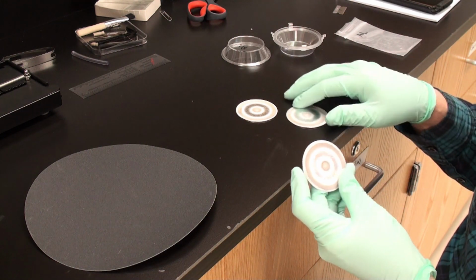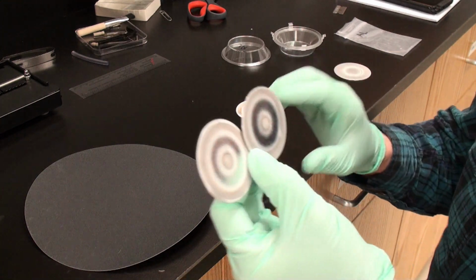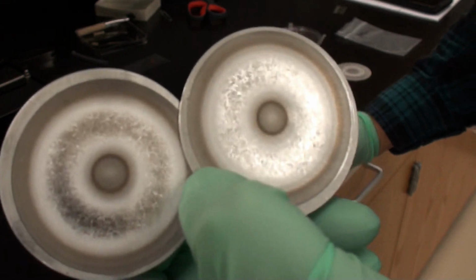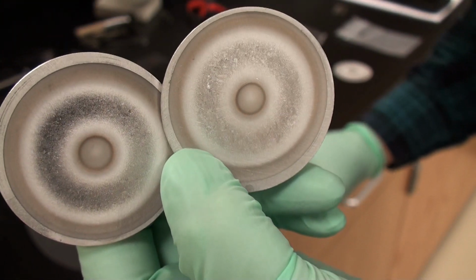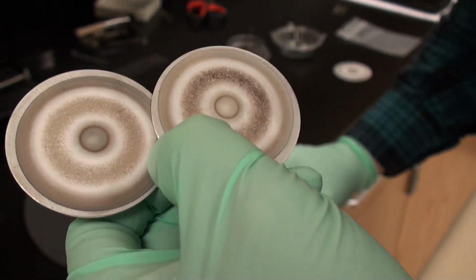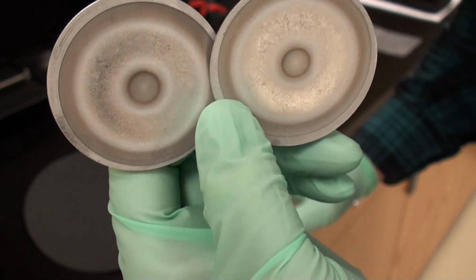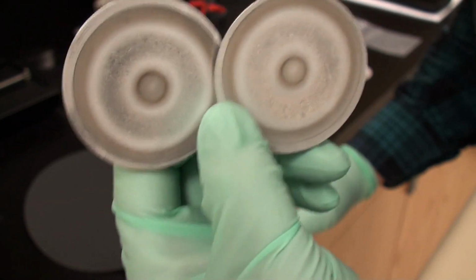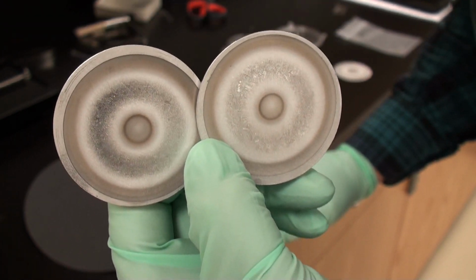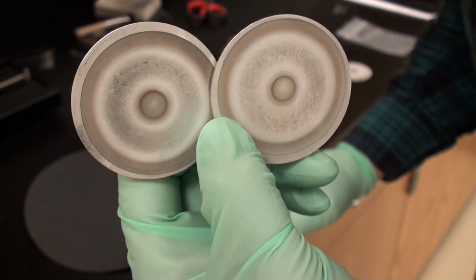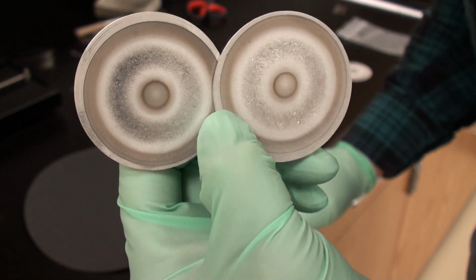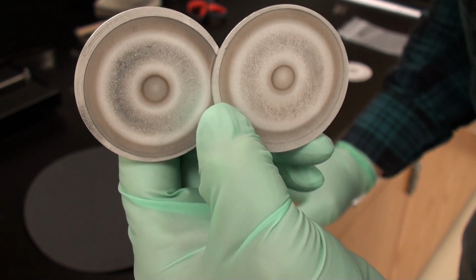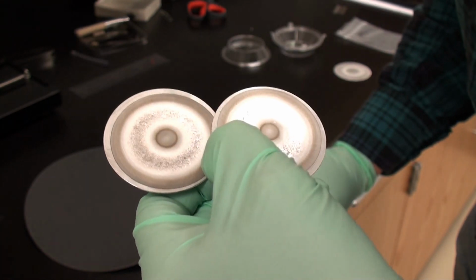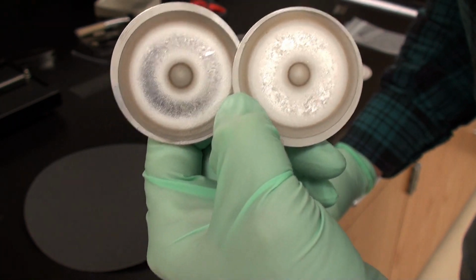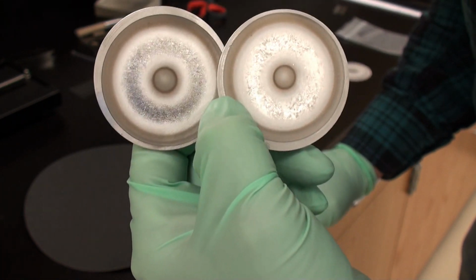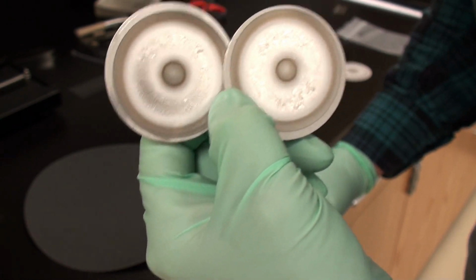These are 3 targets which I've previously used in the Q300. As you can see, there's a very nice clean racetrack. You can see the crystalline structure of the sputtered aluminum. Once prepared and sputtered, I keep these sputter targets in an inert gas cabinet, or at least a cabinet with Drierite to keep the water vapor content and oxygen level low. So these targets do not get coated with oxide and are relatively quick to put back into service if necessary.